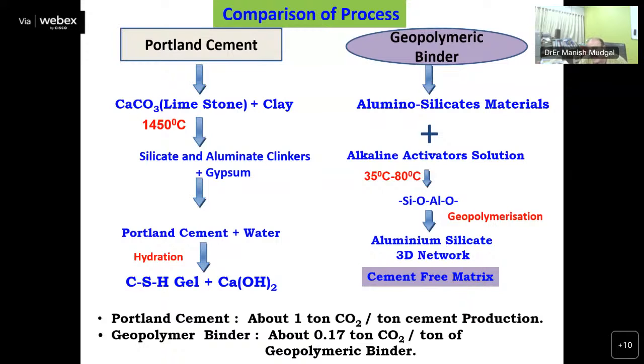Whereas in this system, there is a formation of a Si-O-Al bond 3D network, and only with the drying mechanism you can get the strength. So this geopolymeric concrete does not require any water curing. And we have calculated the carbon dioxide emission from this geopolymeric binder: it is 83% less, meaning only 0.17 tons of carbon dioxide per ton of geopolymeric binder.